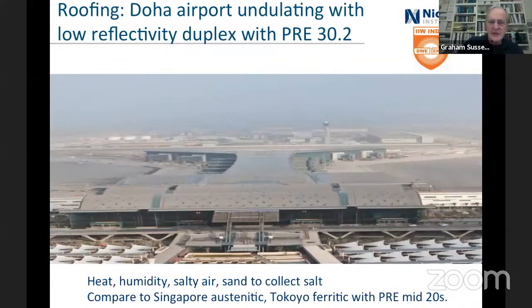Middle East, this is Doha, duplex with a low reflectivity and a PRE of about 30. Heat, humidity, salty air, sand, all collect salt. And compare that to Singapore. The race course has got the galloping horses roof. Tokyo has got a ferritic roof, both with PREs in the mid-20s. And it's simply climate.